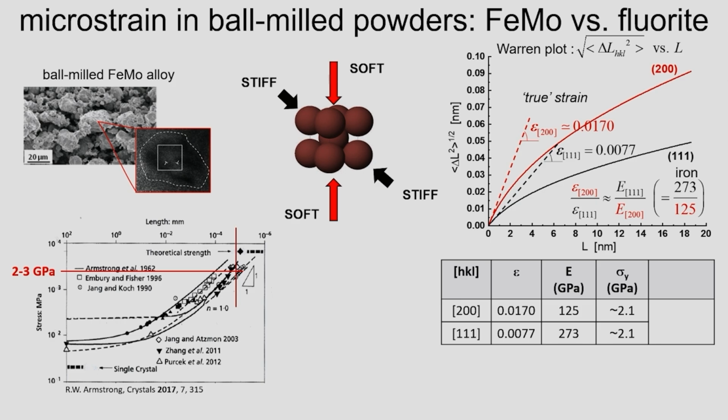But this is just a study where you see a huge variability, whereas we measured it for this specific alloy. And then, if you believe in all of this, if you know the stress and you know the elastic modulus, a very simple formula, the square of the stress divided by 2 times the Young modulus, gives you the resilience, which is in the order of 13 megajoule per cubic meter, which is a huge resilience, by the way, huge.